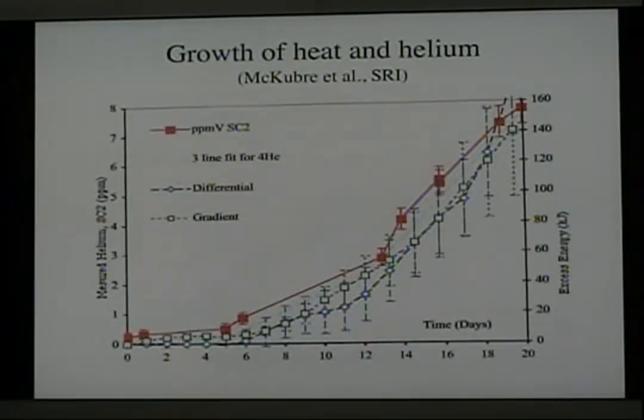Well, here's another example of the relationship between helium production and heat production. In this case, the sample being studied is an ordinary chemical catalyst, which consists of finely divided palladium deposited on charcoal. This was heated in deuterium gas for a period of time, and after a while the helium content of the gas began to rise, and the amount of energy generated by this process also began to increase. The energy is plotted here, and the amount of helium is plotted here. And you can see that these two independent measurements, the helium and the heat, track each other beautifully, going up to 160 kilojoules total energy.